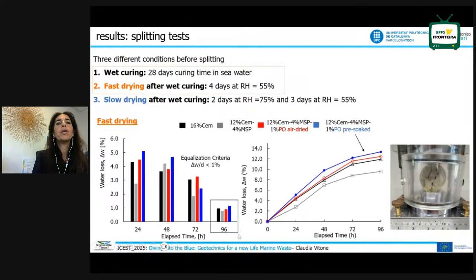If we cumulate the water loss, we obtain also an interesting result, because as you can see here, the maximum water loss is recorded for the mixtures including the pre-soaked fibers. Instead, the lowest one is obtained for the mixtures with the shell powder, the cement and the sediment. So this means that when we use the shell powder alone, water essentially is entrapped in the mixtures. Whereas when we add the fibers, they are essentially bridging, connecting the mixtures to the atmosphere much more.